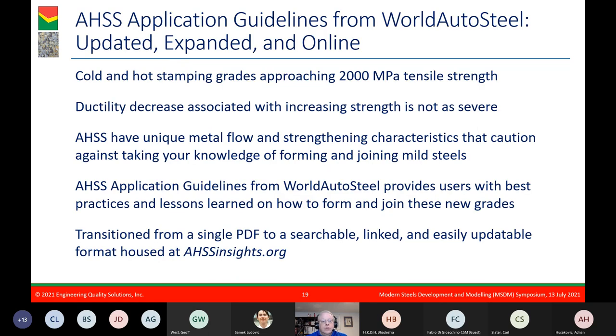The number of new sheet steel grades commercialized over the past 20 years has given manufacturers many more options from which to choose. Some cold stamping options include grades with a 4- or 5-fold increase in tensile strength compared with mild steels, with hot forming grades even stronger. The ductility decrease associated with the increasing strength is not as severe in these new grades. However, there are some unique metal flow and strengthening characteristics that caution against taking your knowledge of forming mild steels and simply upscaling it to address these substantially higher strength steels.